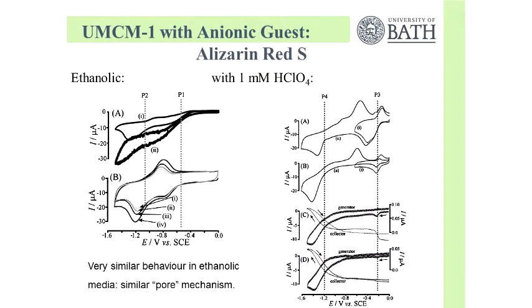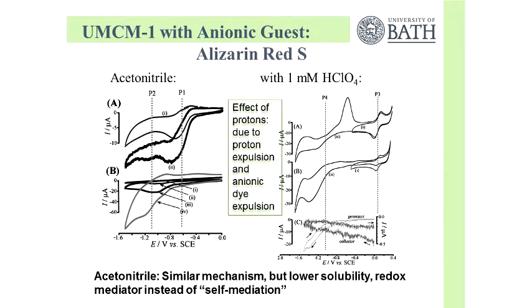We tried different solvents. This was water. In ethanol, it's the same. Process 1, process 2, process 3, process 4. Or in acetonitrile, process 1, process 2, process 3, process 4. So it doesn't depend on what's outside. It's all inside of the material. It's the pore process. It's the alkaline conditions in the pore which actually break up this kind of material. That fits very well with the ferrocene results. It's quite sensitive to redox processes inside to get effective protons due to the proton expulsion. You get alkaline conditions and you get anionic dye expulsion from the pore.